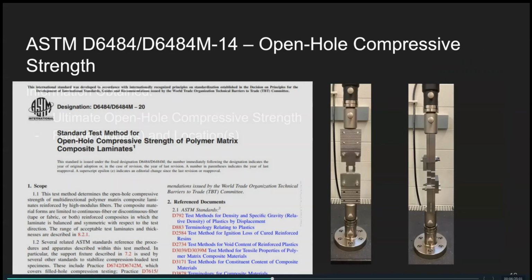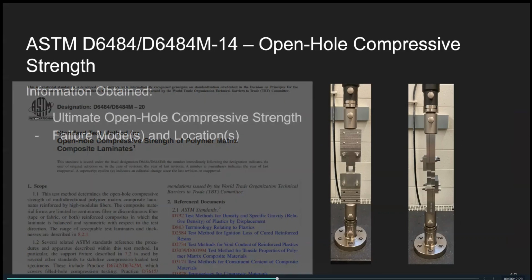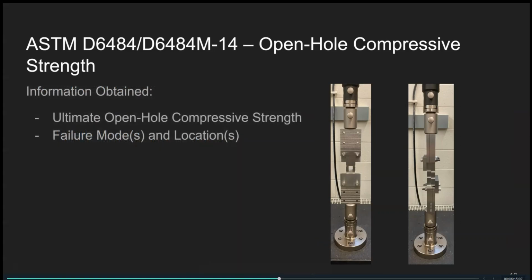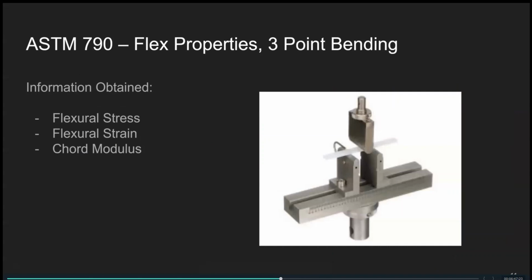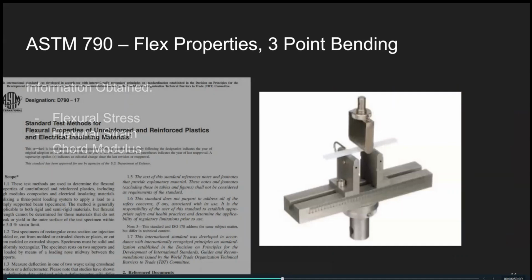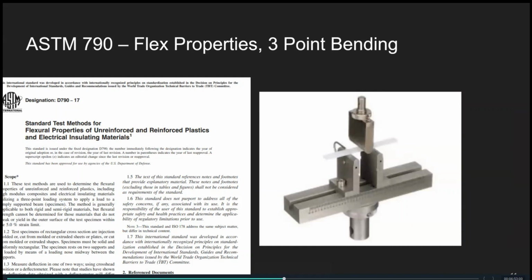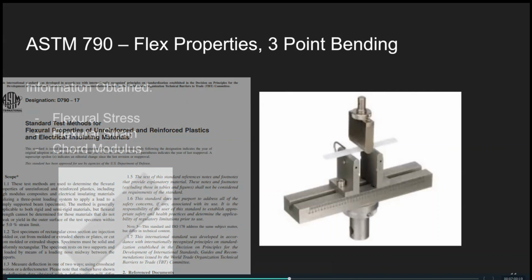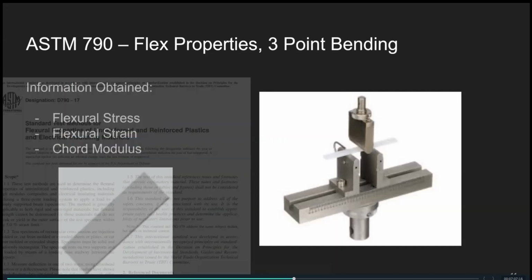And open hole compression, yet again following the same vein of testing, was governed by ASTM D6484, and the ultimate open hole compressive strength and failure modes were determined. 3-point bending, ASTM 790, was then completed. This was a basic 3-point bending test completed on the Instron, where the piece was balanced on the supports and a point was brought down from the top. The flexural stress and strain, as well as the chord modulus, were then determined for these flexural properties.